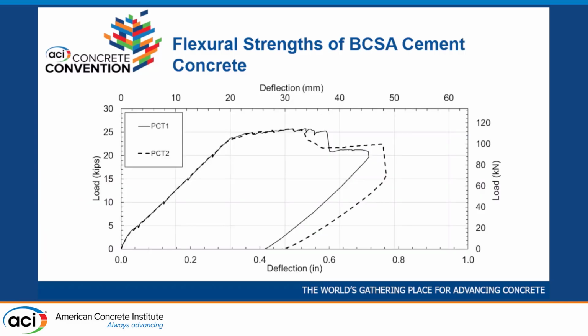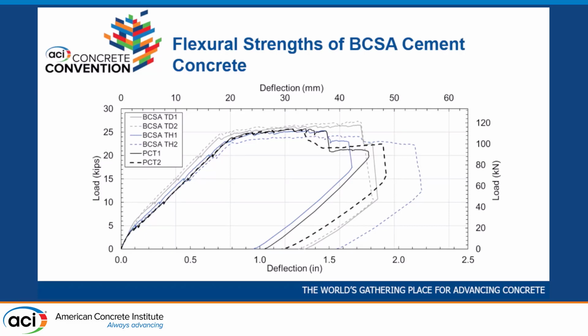We also look at load versus deflection. This is a good way of seeing if the performance of the beams is similar to Portland cement. So here's the Portland cement beams. Here's the BCSA beams that we tested at about 4 or 5 hours of age. And you see they plot right on top of the Portland cement beams. And then these are the BCSA beams that were tested at a day of age. So the performance of all these was very similar. A couple places we really look at are where the cracking occurs down there at the bottom, where yielding occurs. It happens at similar loads and deflections, and then this ductility out here that's indicative of a good tension-controlled reinforced concrete failure. So it's very similar for Portland cement versus BCSA cement.